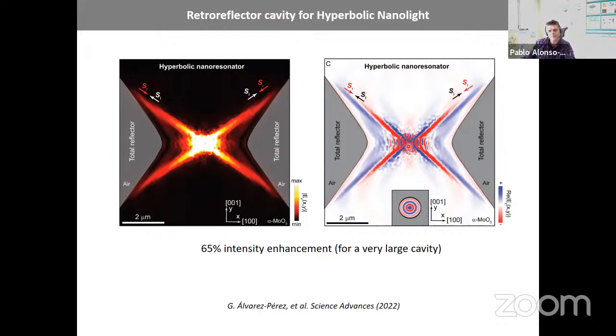If we have the SNOM tip and we make a scan with it all around, we will have only back-reflected waves at this point. Even if we have some signal when we are here, we excite these hyperbolic waves, they go to this boundary, and probably one of all the Ks launched by the tip will come back, but the signal will be very weak. Only at this point, all the waves that emanate from the tip will come back here. So this will dominate the image.